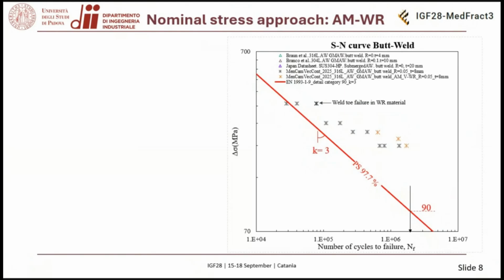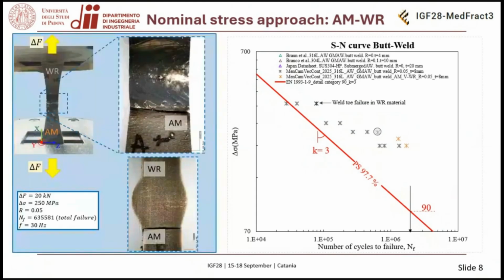Then here you can see also the data about joints with the AM part. And as you can see, they are in good agreement with the fatigue strength of the traditionally manufactured joints. And also in this case, they exhibit an inverse slope that is higher than the one provided by the Eurocode 3. Almost all failures occur at the weld toe on the AM side, and only one failure occurred at the weld toe on the wrought side, so the traditionally manufactured part. And the failure occurs at the weld toe, the most critical one due to the notch effect, and propagates as in the traditionally manufactured welded joints in the interface.